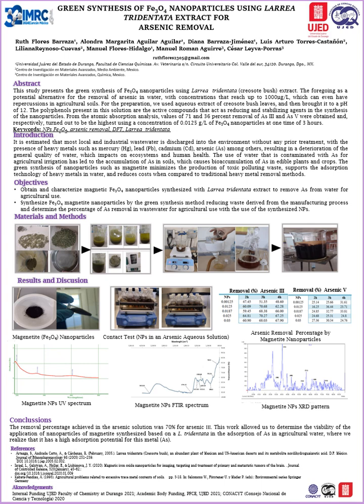As seen in this table, an optimal time of 3 hours was obtained for arsenic 3, obtaining a removal of approximately 70%, and by increasing the contact time, the removal decreases. It could also be observed that the optimal concentration of magnetite nanoparticles is 0.0125 grams per liter, with the best conditions to obtain the greatest removal of arsenic 3.